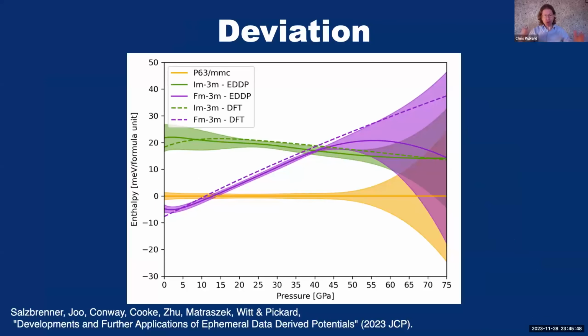Because we have an ensemble or a large number of neural networks, we can look at the standard deviation or the variance of the predictions and use this to make an estimate of the error. Here I've plotted error bars on enthalpy curves, which is nice to see. You don't normally see that with pure DFT results.